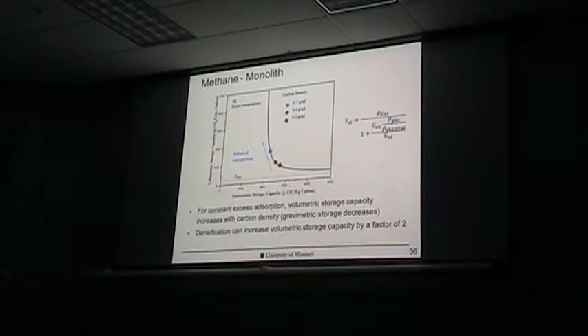So if you look at the red dot here, this is 0.3 grams per milliliter, the density. This is from our pure carbon, from our powder. And if you press it to monolith, you can go up already almost to 0.7 grams per milliliter. So we can increase the density by a factor of 2, which also increases the volumetric storage capacity.